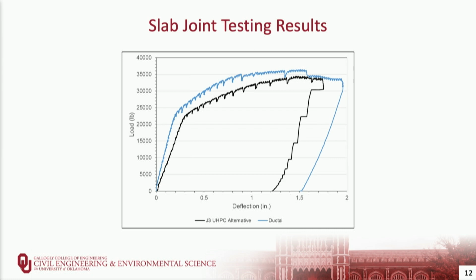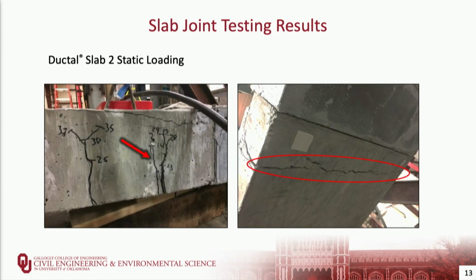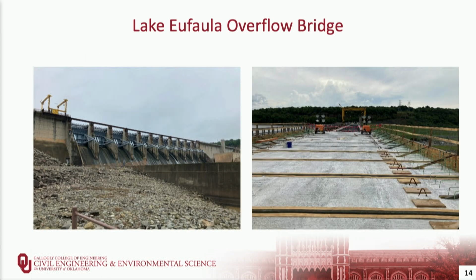This is a graph of load versus deflection for a static load test using the proprietary UHPC and the non-proprietary UHPC. You'll see that they have very similar behavior. There's a slightly higher stiffness for the proprietary material that's related to it having a little bit better bond to the base concrete. But in both cases, we ended up with a connection that actually produced a strength higher than the flexural capacity of the slab by itself. If we look at cracking in those slabs, we see that the majority of cracking occurred out in the base concrete, which is what we would want in terms of making a connection with this material.